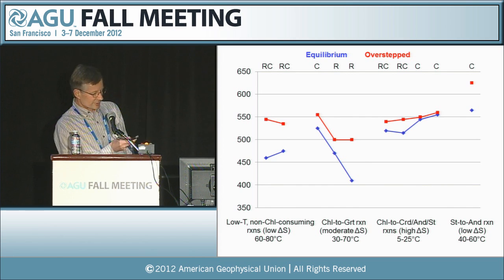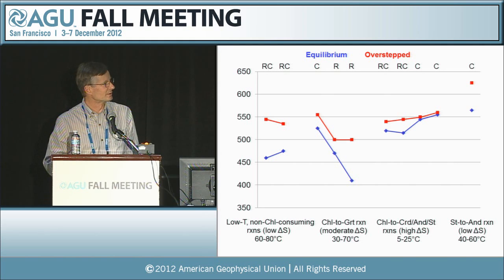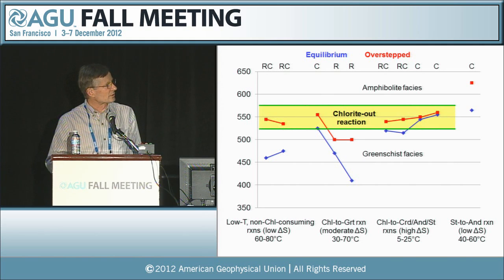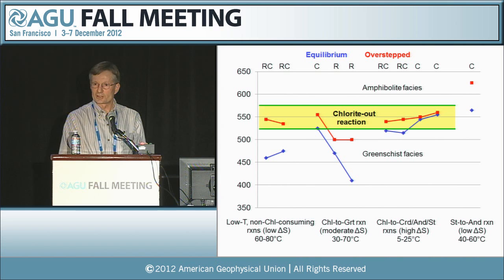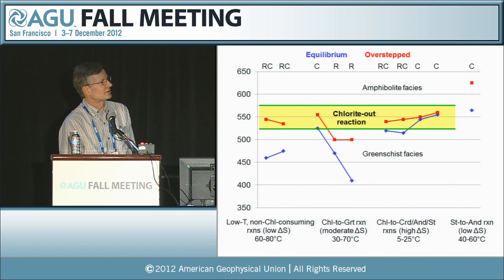One other thing that's kind of interesting about this graph is you can see there are an awful lot of dots which line up around here at the 550 degree temperature line. This generally corresponds to the chlorite out reaction, which is this interval of very high water production and high entropy reaction. And this basically is the dividing line between the greenschist facies and the amphibolite facies.